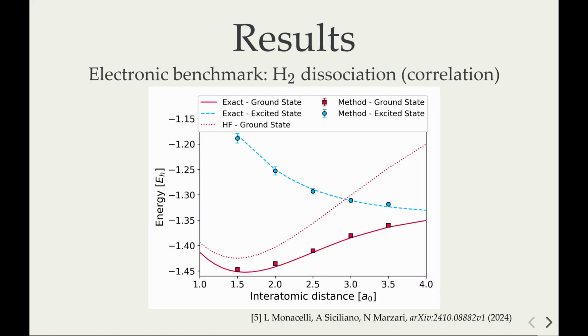Last, before closing, this is what happens in an interacting electronic system like H2. Here we are dissociating the H2 molecule, and you can see the exact results compared with the results of the theory - it works very well. Not only that, this came to me with a high surprise: even in a strongly dissociated regime, this seems to get a very nice result. So this method seems to account for strong correlation, which is something that usually we struggle a lot with.